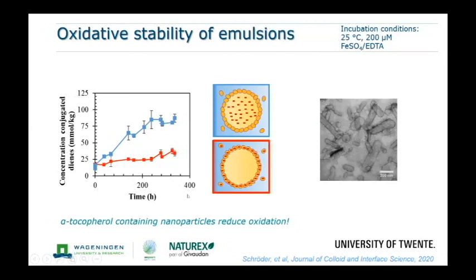If you then look at the oxidative stability, which is on the left graph, you see that the one that has the antioxidant in the particles is very much slower in oxidation than the top one. That has to do with the fact that oxidation is initiated at the interface, and because of the use of particles, we put the antioxidant exactly where it can be most effective. So this is, again, a nice application of nanotechnology that really helps increase the food quality.